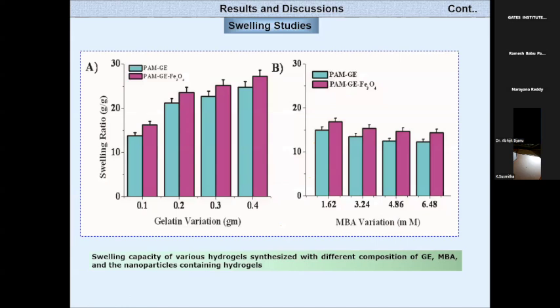After this, for any application, first you have to see the swelling capacity of your hydrogel magnetic nanocomposite. It is a simple study. Once you have developed the hydrogel magnetic nanoparticles, you have to cut them into small pieces and dry them overnight, so that all the water comes out. Then you keep that dried hydrogel in water, only water, for at least 24 hours. Since this is a hydrogel system, it will absorb the water. Why are we doing these swelling studies?